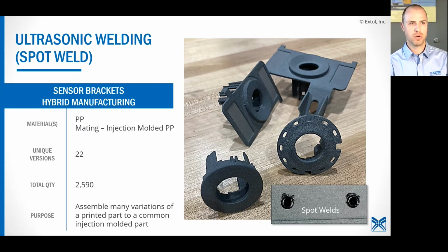And so it just wasn't going to be practical for them to tool up each of those different styles. In this case, there were 22 unique versions of this bracket, and we ended up printing over 2,500 individual pieces for this application. These were the printed component. The larger component was an injection molded component that was much larger and was tooled already. The printed component was welded to that larger polypropylene injection molded component with ultrasonic spot welding. You can see those here in the flatter, thinner areas of that assembly that would be welded to that larger injection molded part.